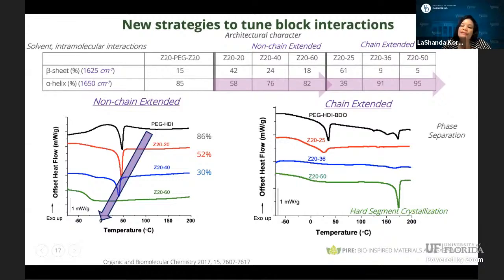So you have for the PEG HDI butanediol, which is the chain extended polyurethane, you can see really nice phase segregation. You have a PEG melting transition, and then you also have a hard domain with multiple melting endotherms. If you would anneal this, you would most likely get to a single melting transition. At Z20-25, you still see the PEG melting transition, but you do not see the hard domain interactions.